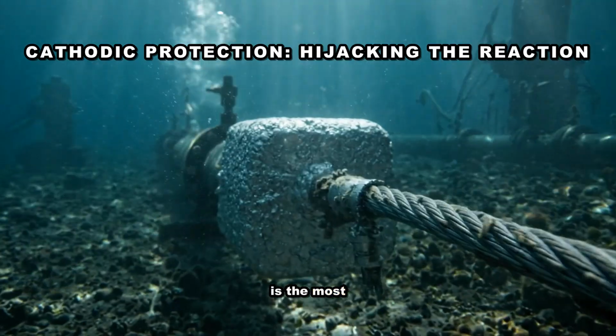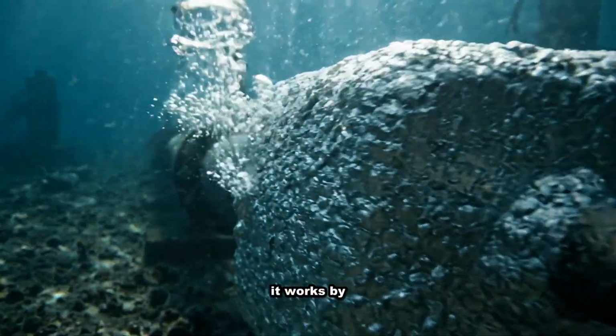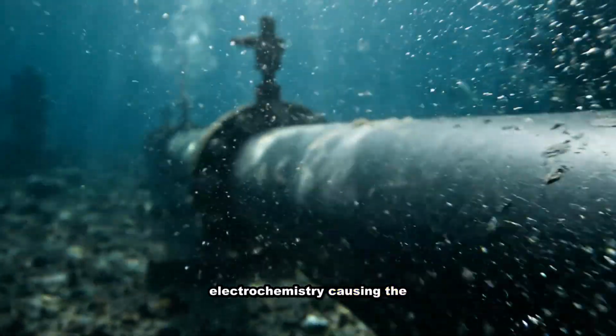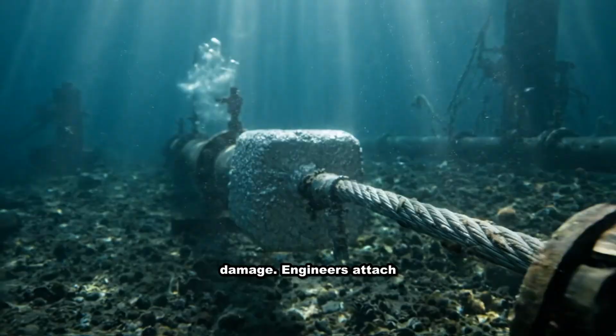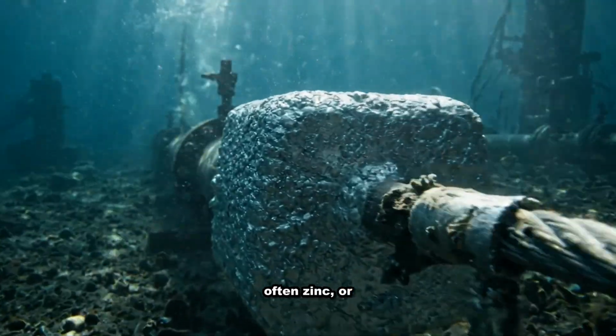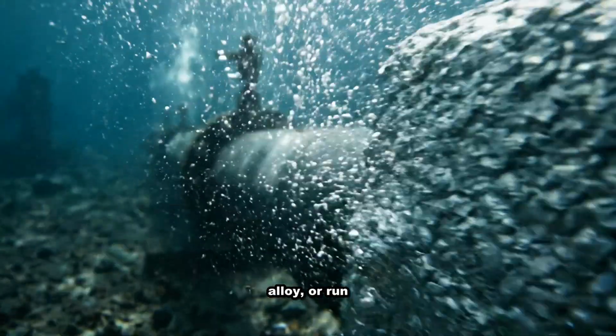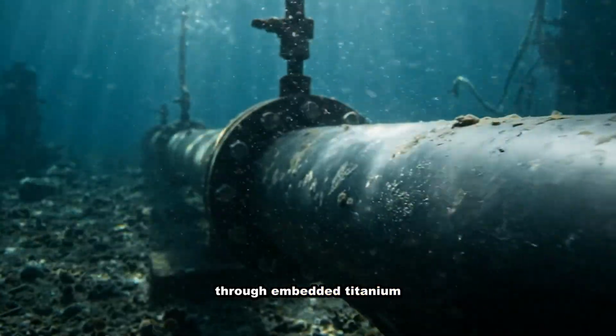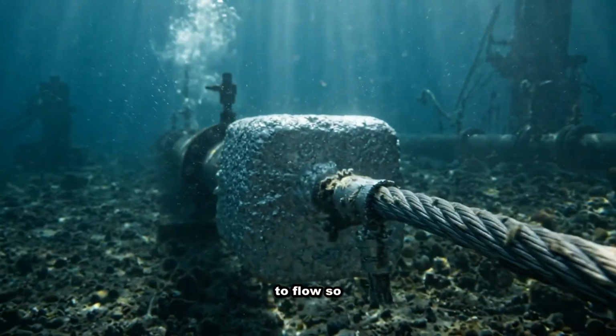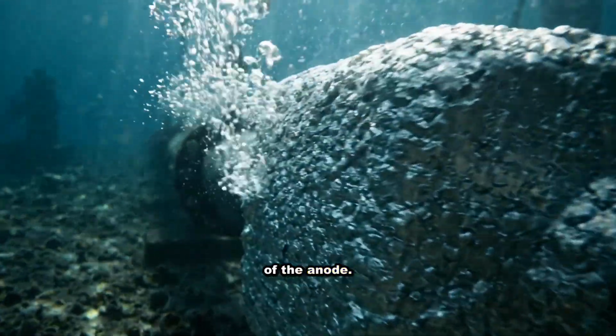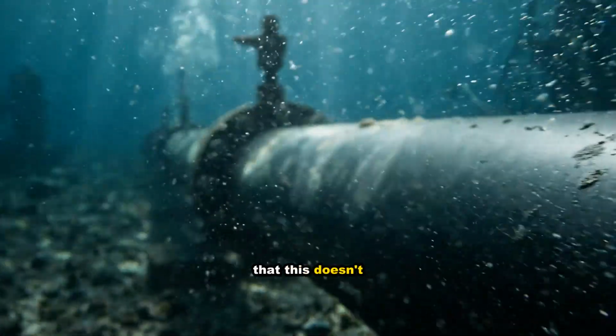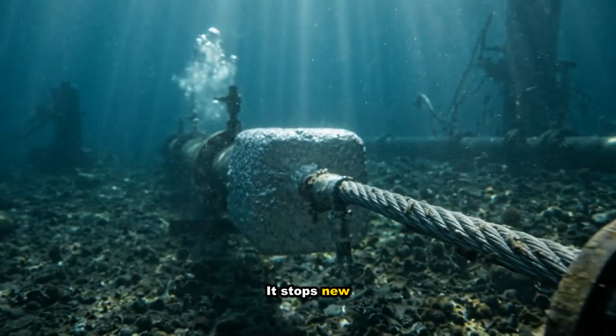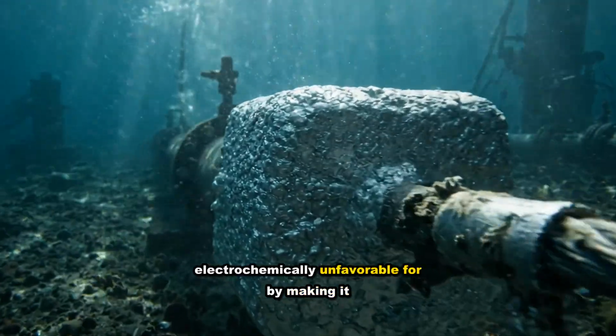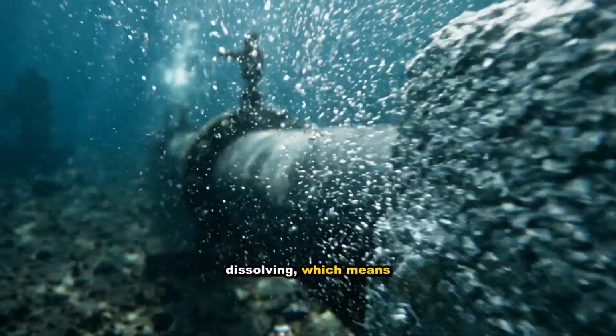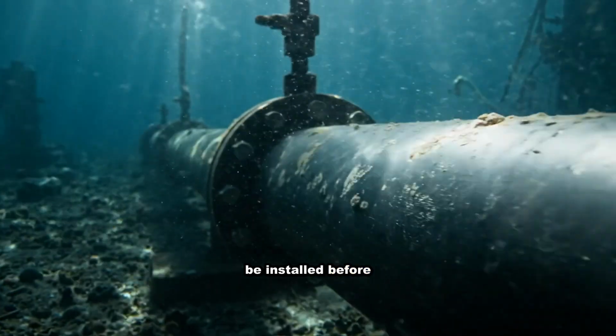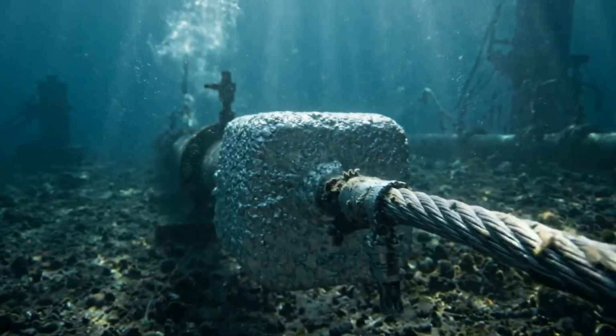Cathodic protection is the most direct countermeasure, and it works by hijacking the same electrochemistry causing the damage. Engineers attach a sacrificial anode, often zinc, or a specially designed alloy, or run an impressed current through embedded titanium mesh, forcing electrons to flow so the rebar becomes the cathode instead of the anode. What matters is that this doesn't repair existing damage. It stops new corrosion from starting by making it electrochemically unfavorable for iron to keep dissolving, which means it has to be installed before the structure looks like it needs anything at all.